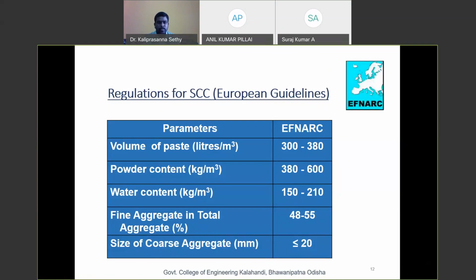they have given some ranges to decide the parameters: volume of paste in liters per meter cube should be in this 300 to 380, and powder content. You should not be confused with this powder content. Powder is nothing but, though we are not using cement alone here, we are using both cement and slag. So instead of saying cement plus slag, I am saying powder content, and it is given in the range of 380 to 600 kg per meter cube. And water content should be within this range, 150 to 210 kg per meter cube, as per EFNARC guidelines.